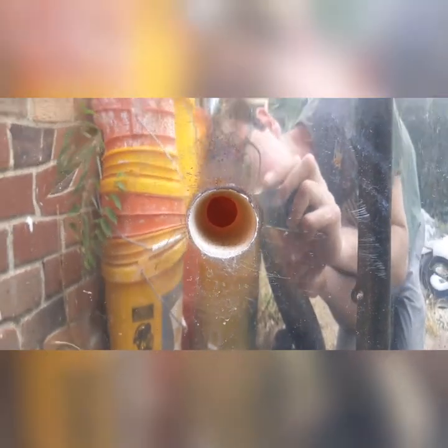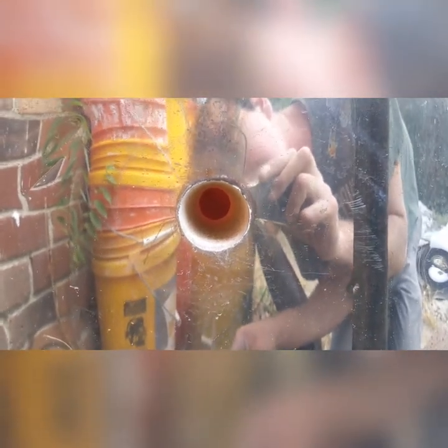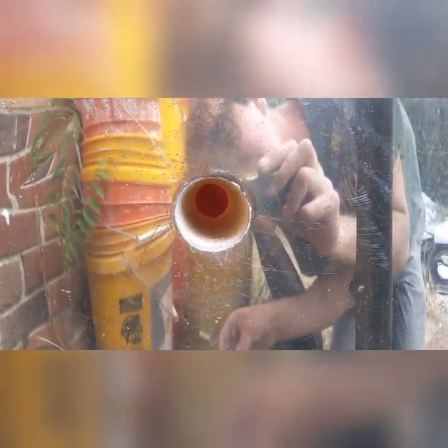I'm here at the center peephole of the kiln. You can see the top and the bottom of the kiln — I'm roughly in the center, and I've got this nice dull red color, which means that we're past the danger zone for pots breaking in quartz inversion. So I'll now probably turn the kiln up a good bit, and then once I reach about 1800 degrees, I'll put it in body reduction. I'll see you again for body reduction.